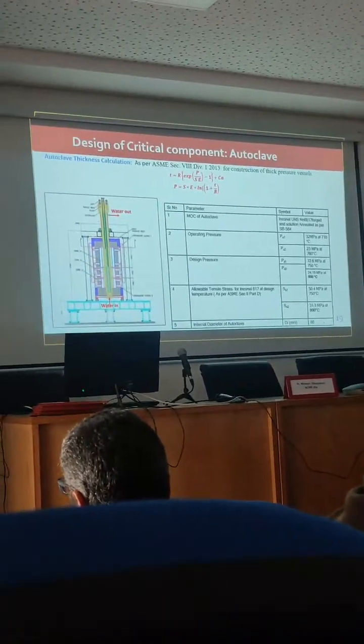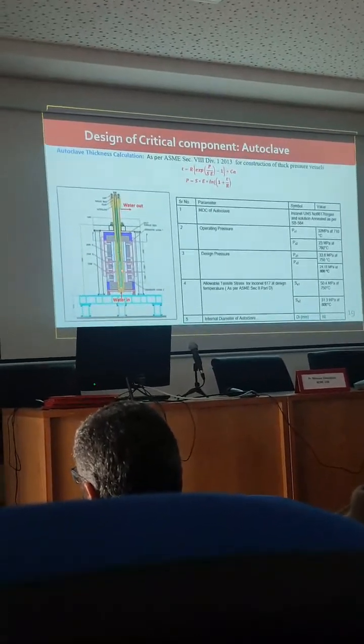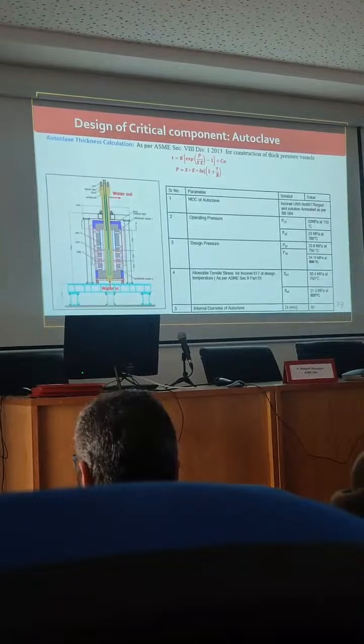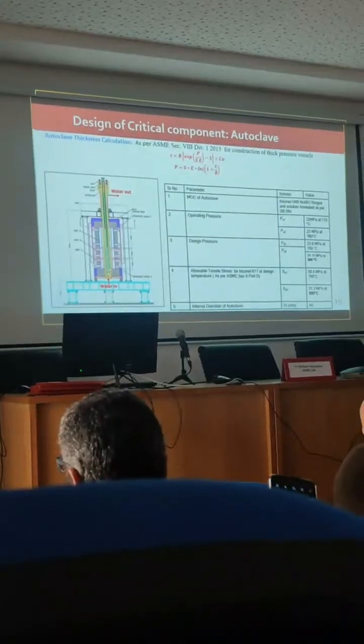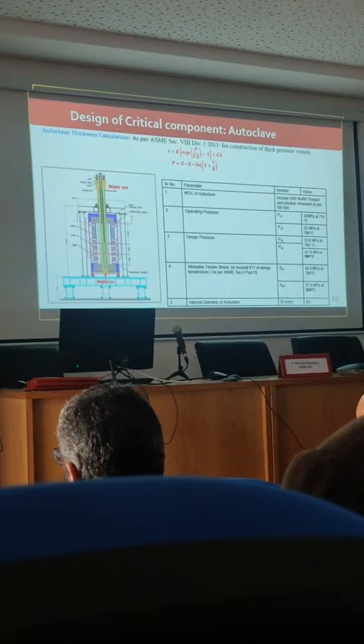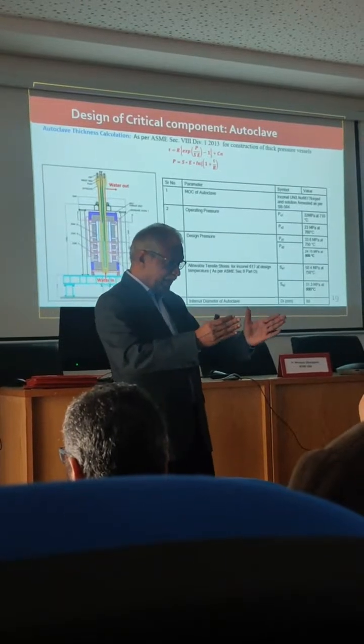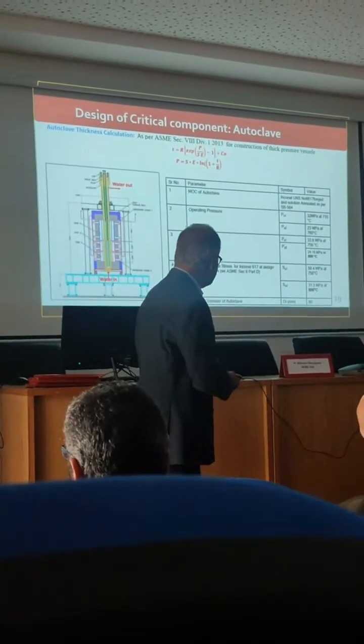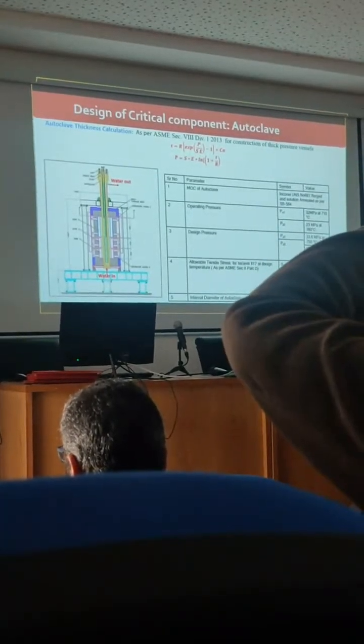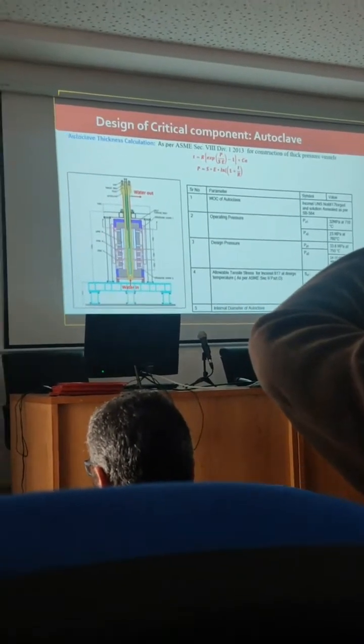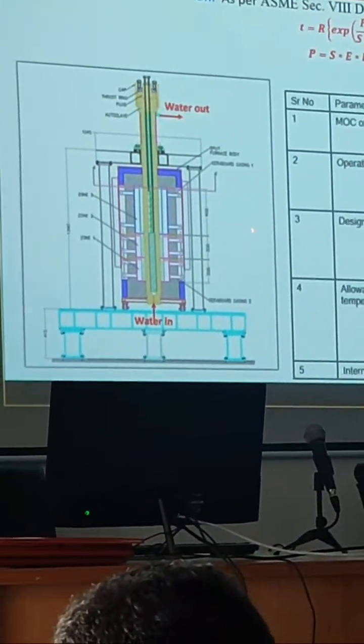Now this is kind of the autoclave. This is high pressure. So water gets in here, raises the temperature. You have samples here. No problem. Issues are plenty here. The mechanical engineers know that if I am going to make an autoclave, working at high temperature, high pressure, I apply 100 megapascal, the wall thickness is this much, right? Heat transfer becomes a problem. The surface temperature becomes beyond the values. So you need to do heat transfer and mass transfer calculations here to optimize the overall system.